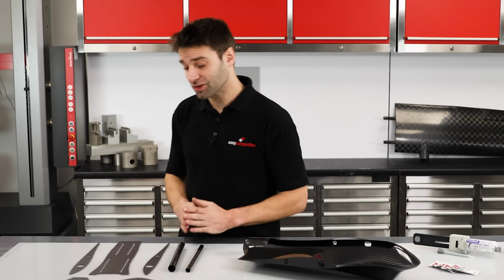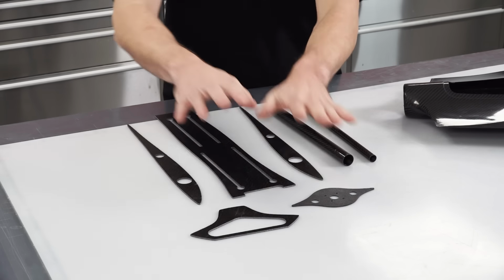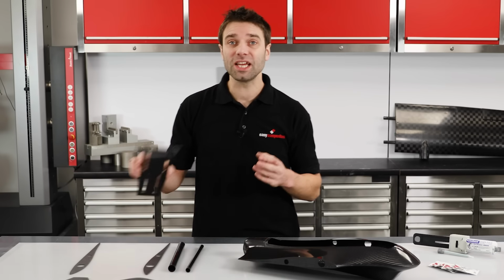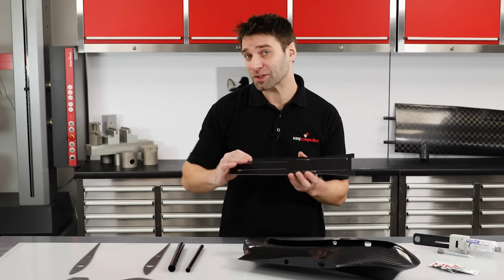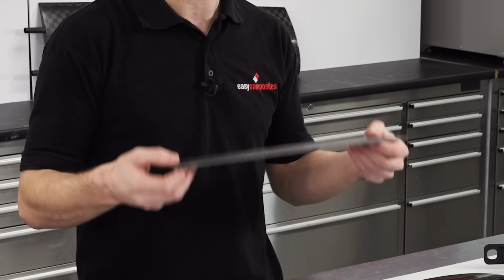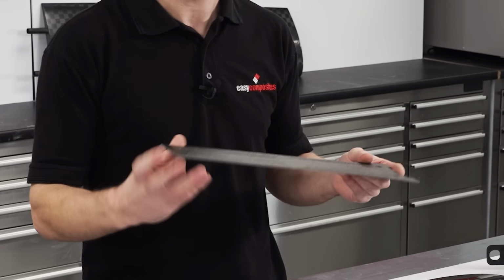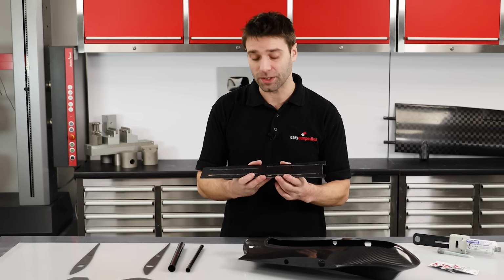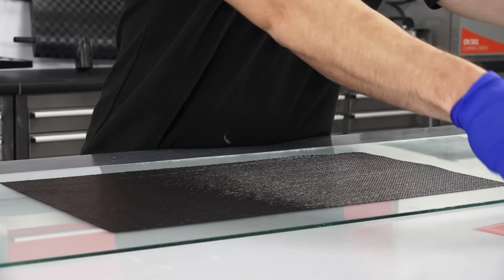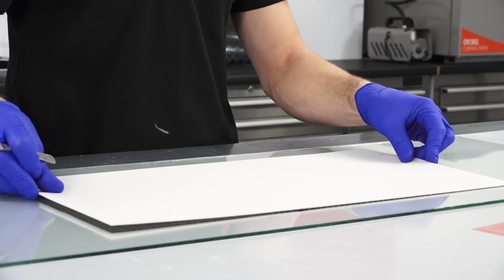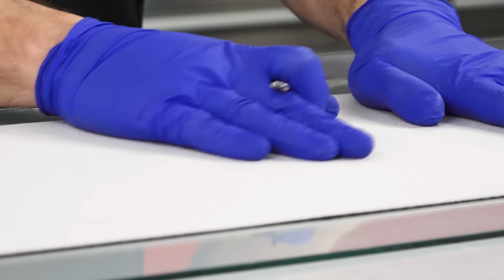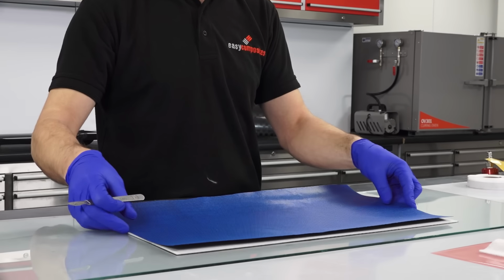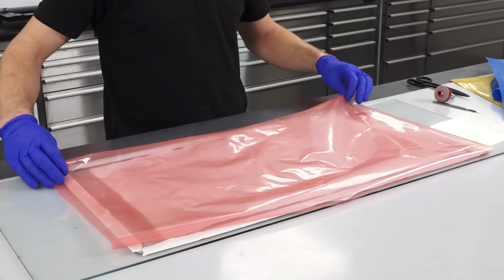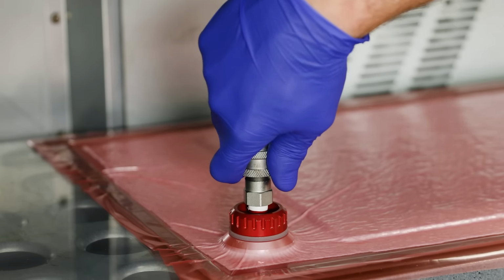With the main fuselage component complete, we can now move on to the internal structure. So we've got the floors, the ribs, the bulkheads and the spar tubes. And to achieve the maximum stiffness for the minimum possible weight, these parts have been made from a lightweight carbon fibre sandwich panel, and this is very common in UAV construction. The panel was made using a single ply of 210 gram prepreg carbon fibre, either side of a sheet of 3mm Rohacell PMI foam. This was then vacuum bagged against a sheet of glass and oven cured following the standard XC110 cure cycle.